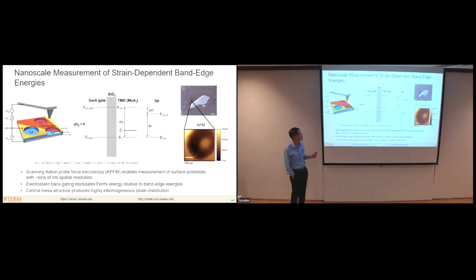And what that allows us to do is we apply the backgate voltage, then it's possible to modulate the band edge energies and the carrier concentrations in the TMD layer. All right, and we'll see why that's a useful thing to do in a minute. This over here shows just an optical microscope image of an array of these holes. I know it's a little hard to see in here. This region outlined in red is where there is a monolayer of molybdenum disulfide, and this is an AFM image of one of the holes shown over here.